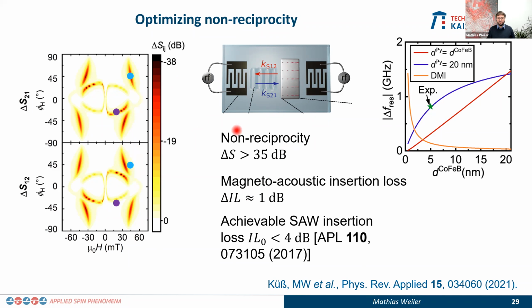Okay, and this non-reciprocity in such a structure can now reach 35 dB, and that's already a useful value. We have some insertion loss compared to a device without the magnetic film. When you put the magnetic film here, you see that the performance is about 1 dB worse. Okay, and then of course we have the bare performance of these two IDTs, and that of course goes back to what I showed you before.